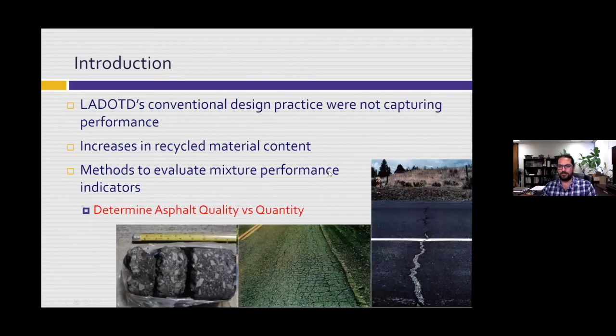Okay, so why did we think we needed to get there? As most states go, Louisiana DOTD's conventional design practice was to use volumetrics as design. And those volumetrics, as we increase the amount of recycled content, we're not doing a good job in picking up potential issues, whether it was compatibility issues or an aging issue or an oxidation issue in our field performance. We got really good at making sure our mixtures didn't rut, but in that process, we ended up with mixtures that were subject to premature cracking.